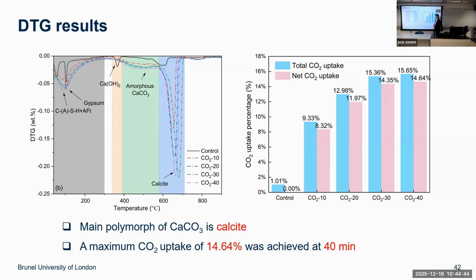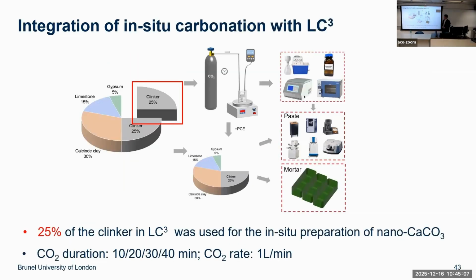We also try to find the morphology. Calcium carbonate has three morphologies, some more stable, some less stable. We find that the main morphology is calcite, and we can uptake or sequestrate 14.6% with 40 minutes injection.